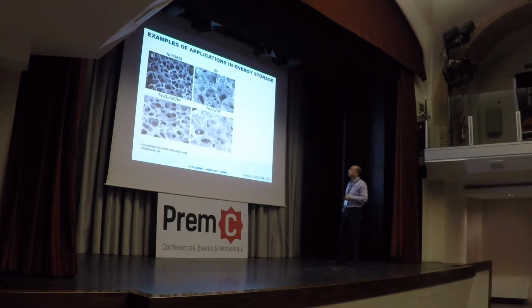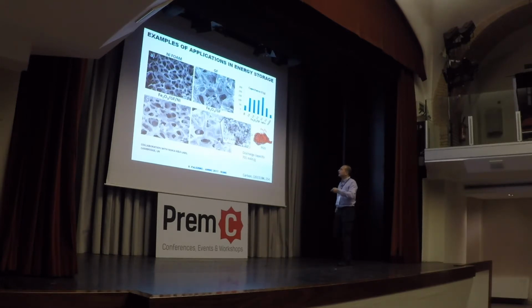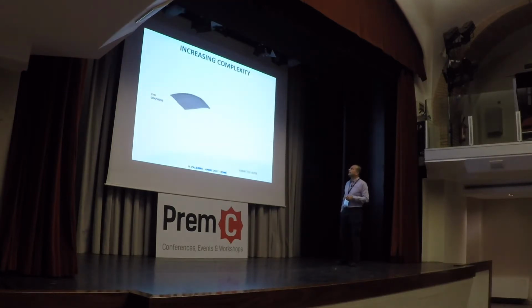On the mesoscale you don't see a lot of difference, but it's coated by a porous layer of iron oxide. Given that it's all done in solution, you can really tune the ratio between the two to maximize the capacitance. And well, we also did a characterization. This was used in lithium cells. It's a collaboration done with Nokia R&D Labs, and you can refer to this paper for more details.